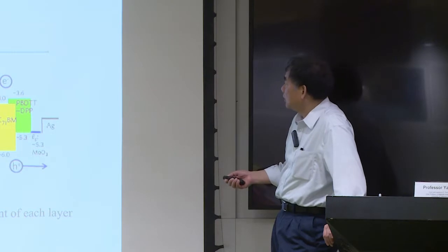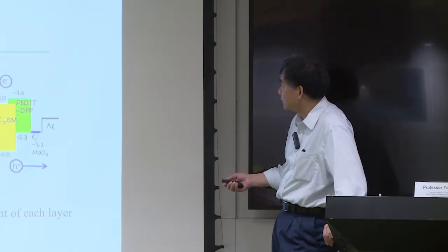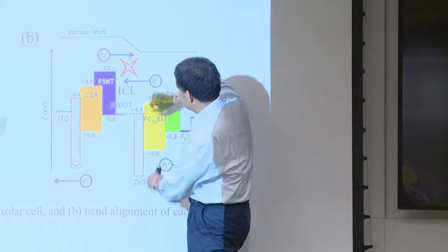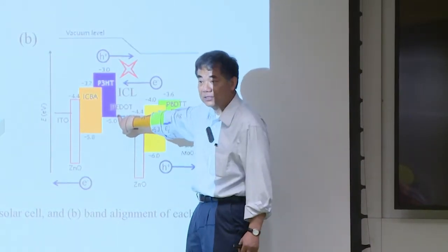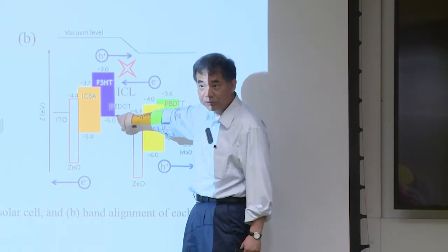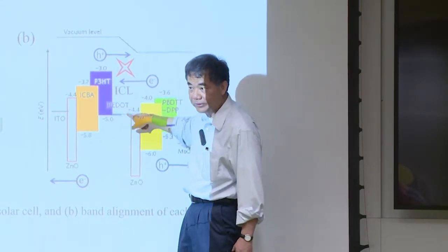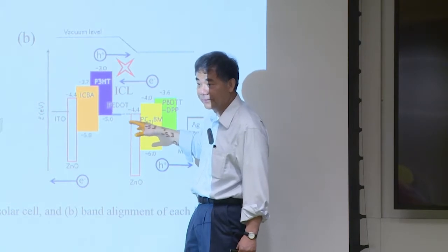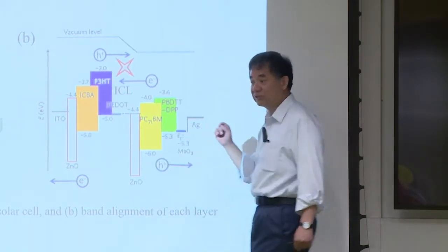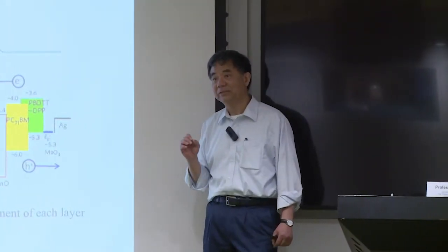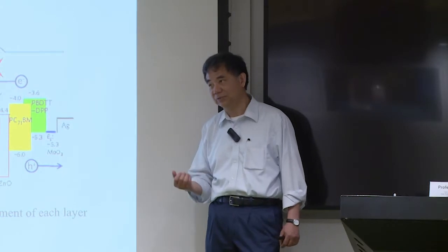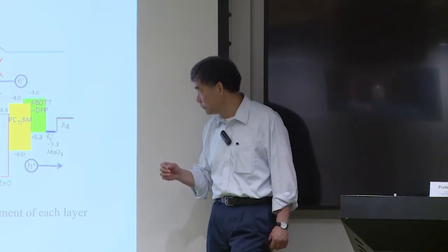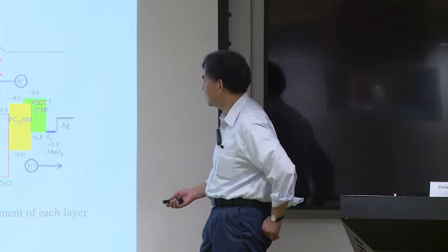So that's the typical energy diagram of the tandem solar cell. You think about these two solar cells, they stack together with a wire. This wire must be transparent optically. And number two, it must have very small resistance. So combining these two, that's the key. It must be processable. Just making the transparent conductor in between is a technical challenge, because a conductor has electrons. Electrons have this plasmonic effect or the free electron effect. It picks up the charges. So that's why those difficulties come from.